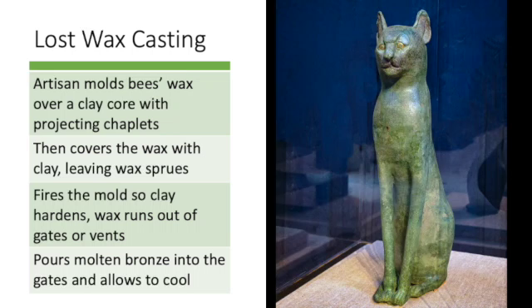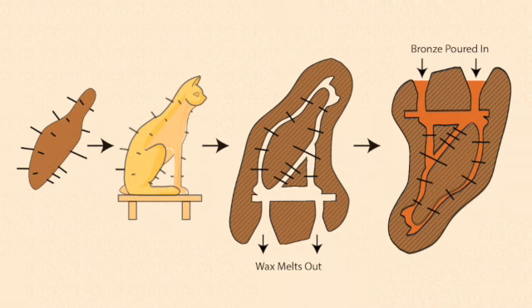One way to cast bronzes with very complex shapes is the lost wax method. The artisan molds the shape in wax over a clay core called an investment. Copper or bronze pins, called chaplets, that were inserted in the clay investment protrude through the wax. The artisan then encases the wax model with clay, leaving some wax extension called sprues. Heating the mold melts the wax and allows it to run out through these sprues, while those pins or chaplets maintain the gap between the outer and inner parts of the mold. With the mold upended, the artisan can then pour molten bronze into the mold through the gaps that were left by the sprues, called gates.